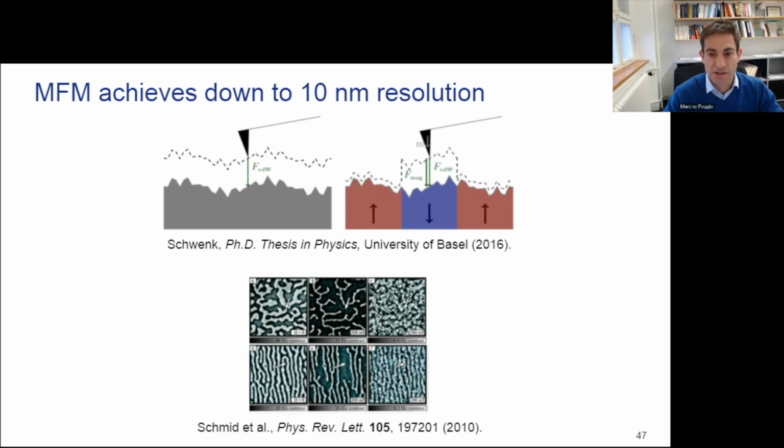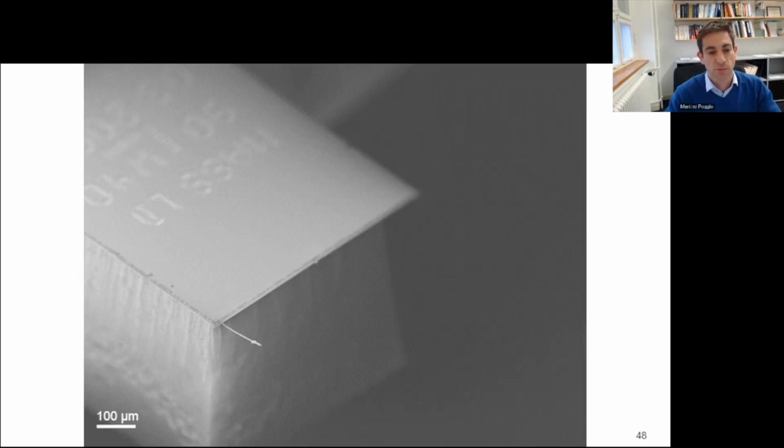It is not an especially sensitive technique to small fields, and it can be highly invasive because of the highly magnetic tip. It's basically intended more for strongly magnetic samples and high spatial resolution. Okay, but in fact, if you just work on the mechanical transducer side and try to use transducers which are softer, basically sensitive to smaller magnetic forces and magnetic force gradients, you can make an MFM which is able to image more subtle magnetic field patterns and is more sensitive.